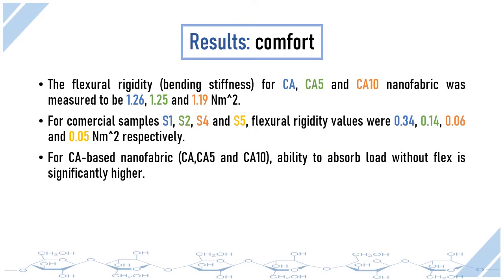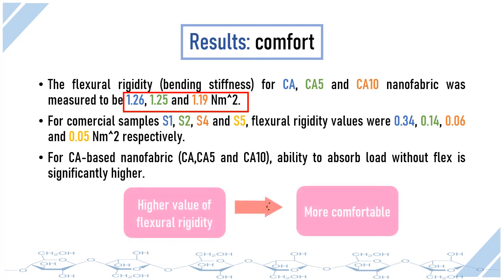Comfort of the fabric was quantified in terms of flexural rigidity and surface roughness. Flexural rigidity is an important parameter for textile fabrics when used to support load without flexing, as is the case here for sanitary napkins. As we can observe for CA-based nanofabric, the ability to absorb load without flex is significantly higher. Higher value of flexural rigidity for CA nanofiber sample makes them more comfortable even as compared to commercial samples.